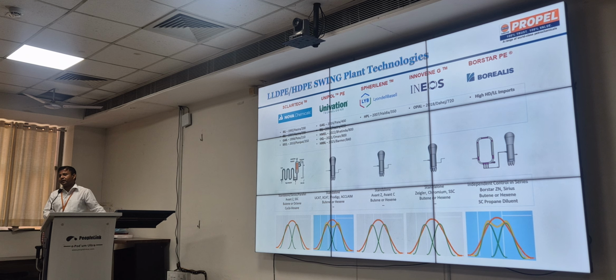they are getting equal dart impact per micron. Generally, with a normal Ziegler-Natta based catalyst, if you are producing the LLDP film grade based on butene as a comonomer, you are getting a dart impact of hardly 3.5 to 4 gram per micron. If you are using octene with the same Ziegler-Natta catalyst, you can get hardly 6 to 7. But if you are using the metallocene grade, you can get up to 25 gram per micron. So this is the difference in performance of the properties of the grade produced from the Ziegler-Natta base and the metallocene catalyst.